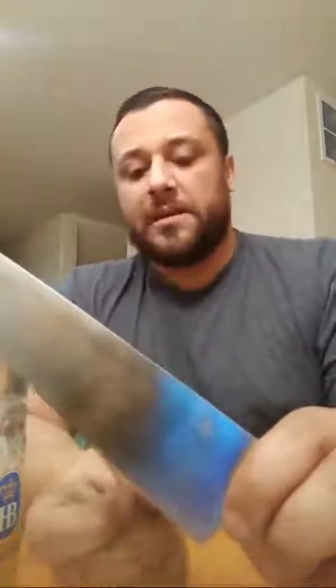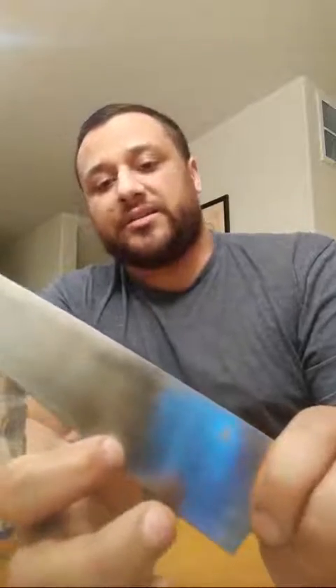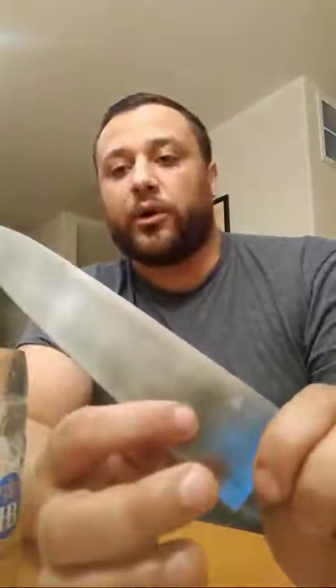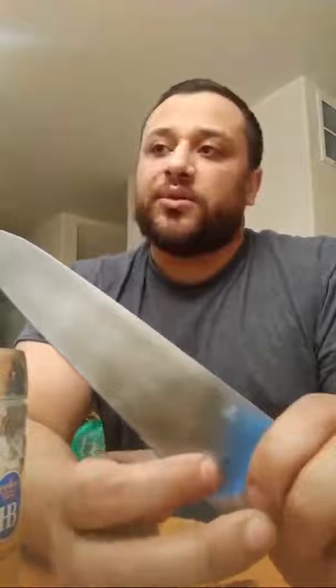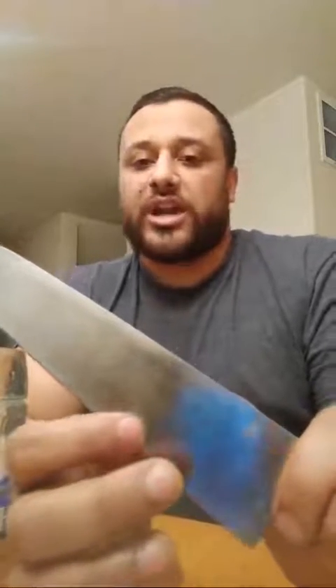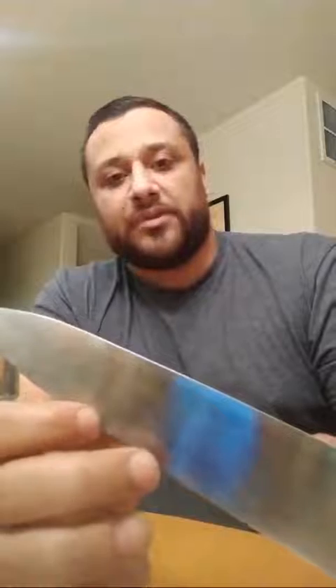The problem with hard chroming is that there was some discussion that you would increase hydrogen embrittlement. If you didn't hard chrome it in a way to then directly temper it after it's been applied with a flash chrome, you would cause some hydrogen to build up between the steel and the hard chrome jacket and embrittle the steel. So it was not ideal.